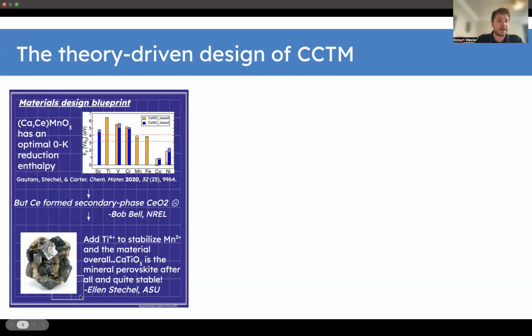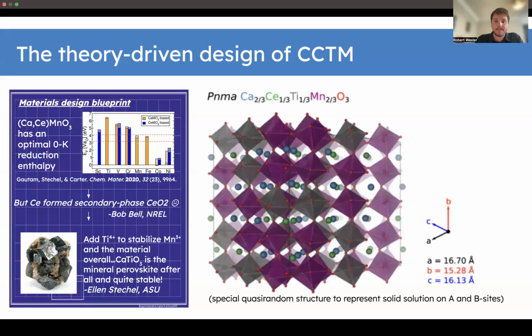additional insight came from Ellen Stechel at ASU, who suggested that we potentially add titanium 4+ to stabilize manganese in the 3+ oxidation state, and also just generally the material overall, because calcium titanate shown here is a mineral. It is the mineral perovskite, and so after all, it's quite stable. So with that, initial theoretical input plus synthetic feedback and some additional general materials intuition, we were able to arrive at a composition